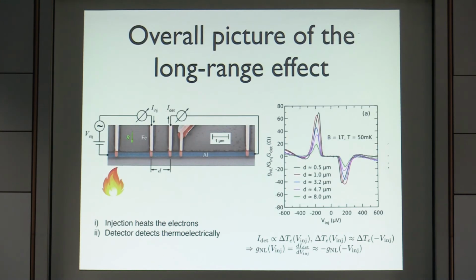In this case, based on this analysis, we already know what happened in this first experiment. Schematically, what happens is that the injection here, where the injection voltage was above the superconducting gap, heated up this superconductor. And the heat doesn't decay that fast at low temperatures, especially in superconductors.